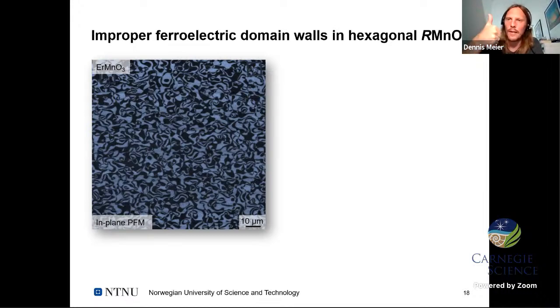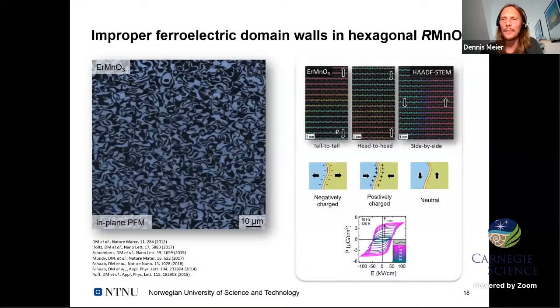Dark means polarization points up, bright means polarization points down. And what you can right away see in this material, even though the polarization is uniaxial, so we only have polarization along the z-axis, the material doesn't really care. The domain walls are meandering around as if there would be no preferred direction. And that's the key point here. We have the structural phase transition that determines the domain pattern. Ferroelectricity comes in only as a secondary effect and has to adapt to what's already there. And because of that, we then get, again, very specific domain walls.